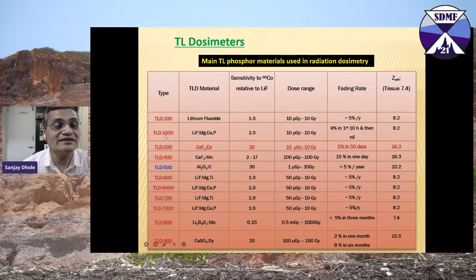So if you go for TLD-100H, which is lithium fluoride doped with magnesium, copper, and phosphorus, then you can have 10 microgray to 10 gray again. So its relative sensitivity is 1 as compared to cobalt-60 and LiF. Okay. The last one is TLD-900, and why lithium fluoride 100? Because the 100 is nothing but the number which is given as far as their annealing temperature and other things are concerned. So TLD-900 is calcium sulphate doped with dysprosium, whose relative sensitivity is 20 as compared to lithium fluoride, and it can go up to 100 microgray to 100 gray.